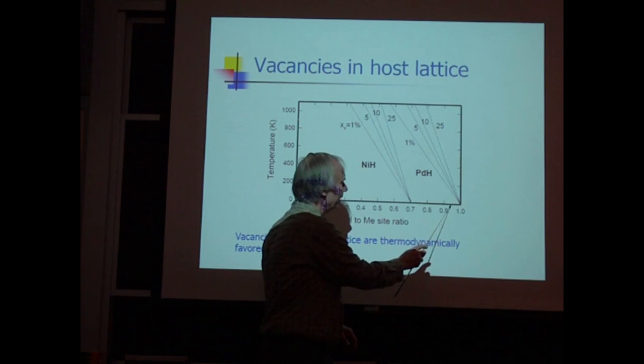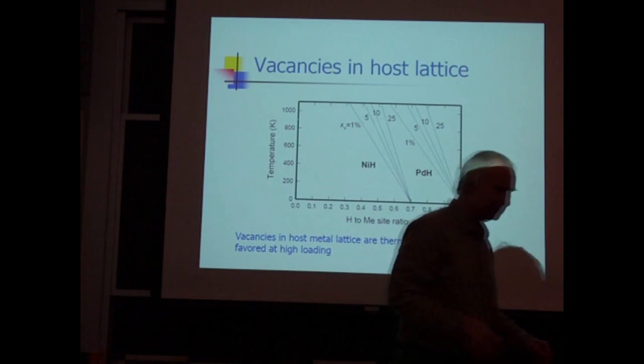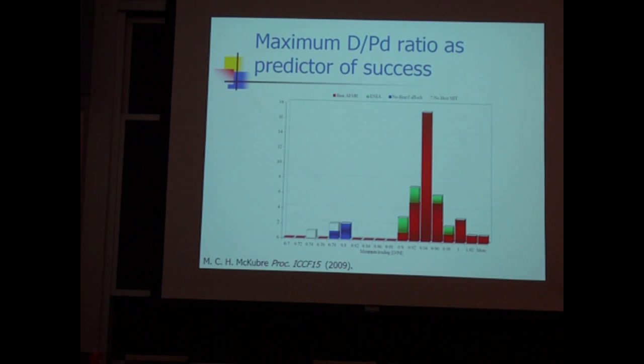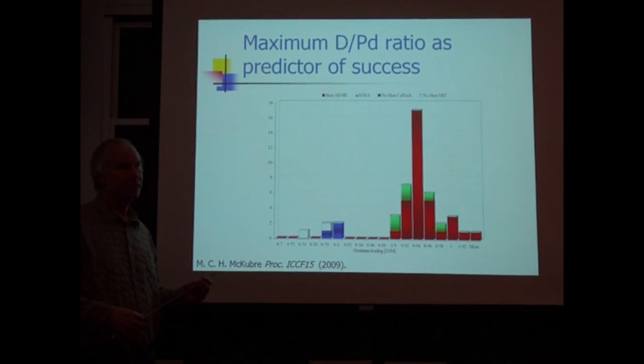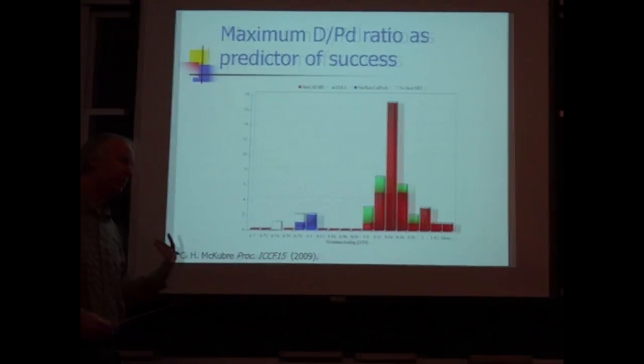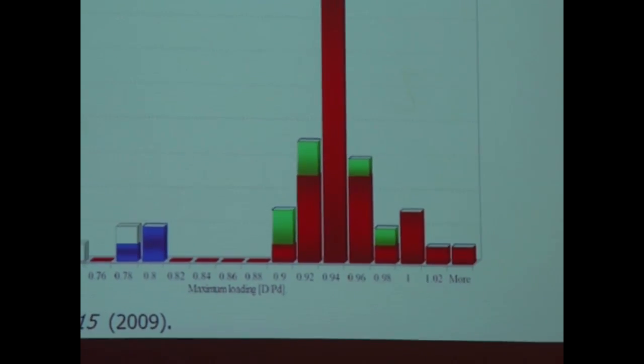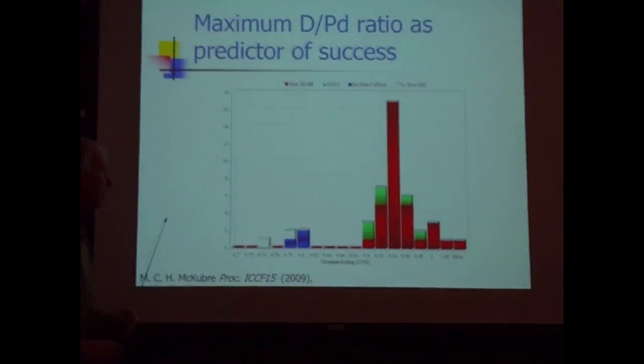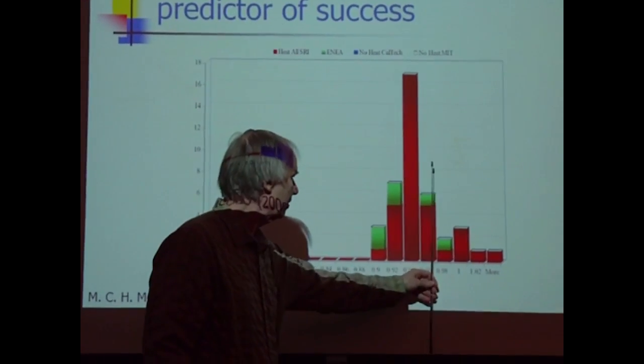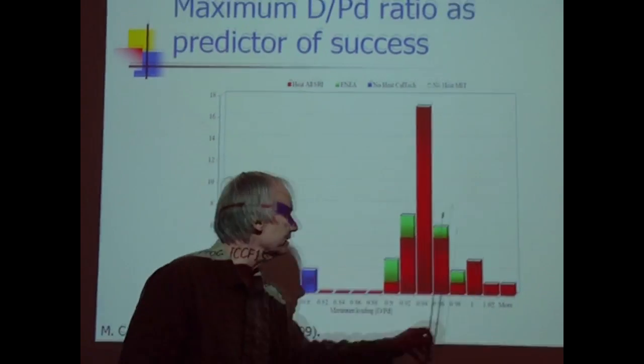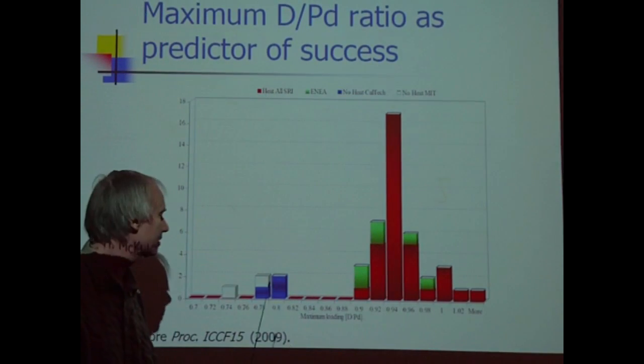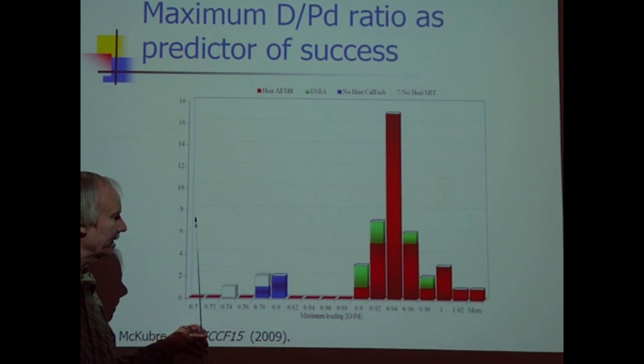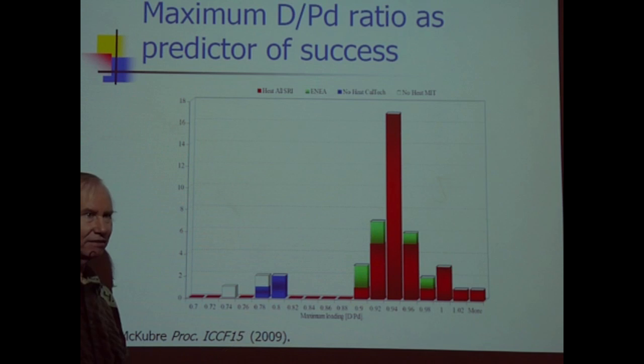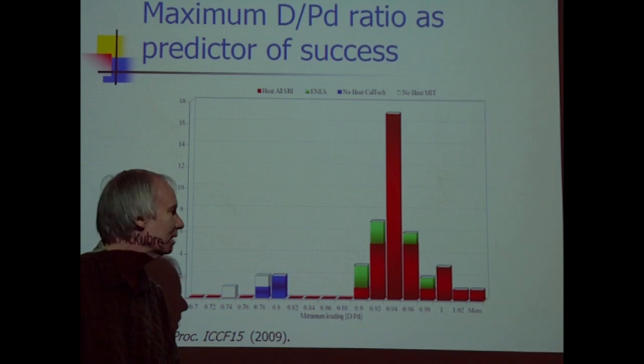Now the 0.95 number here is interesting to me, because that suggests that if I go back to the SRI data, which segregated experiments which worked versus experiments that didn't work as a function of peak loading during the course of the experiment, then we see here's 0.94, 0.96. So these are all positive results. Red is at SRI, green is at ENEA. And back here are the Caltech and MIT negative results. The peak loading was nowhere near close enough to, or high enough to do anybody any good.